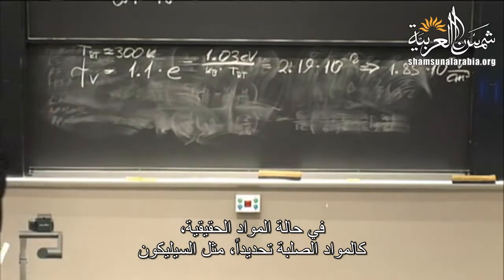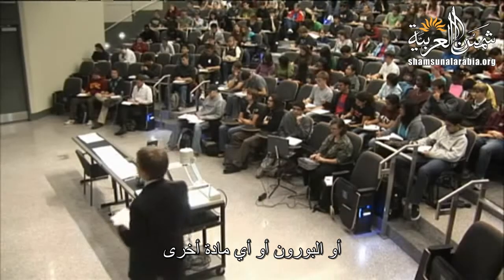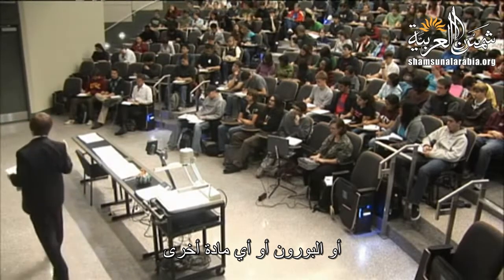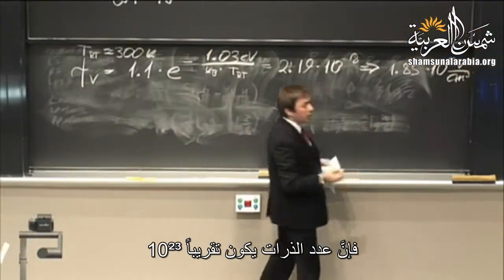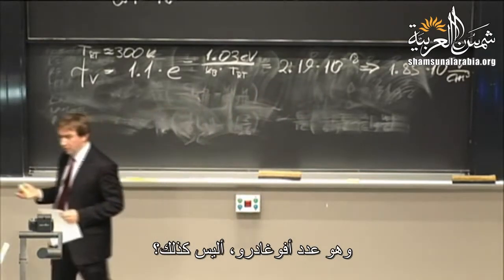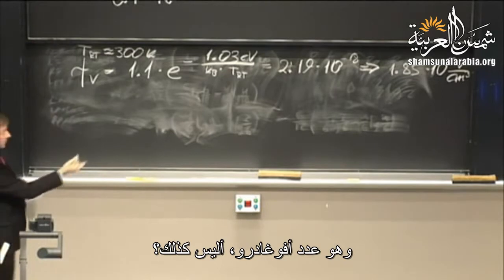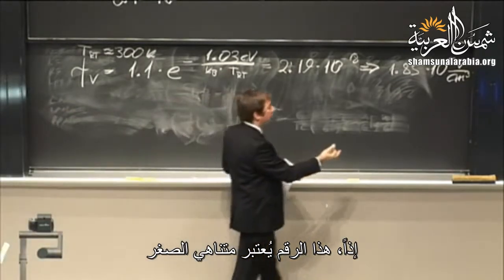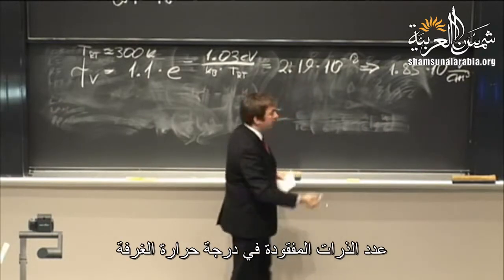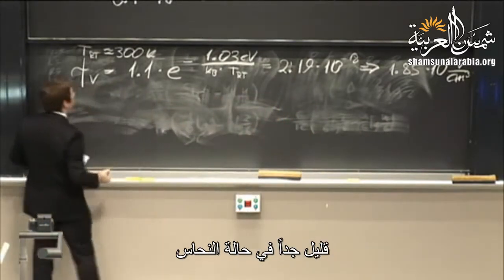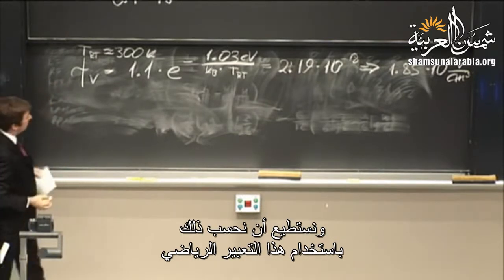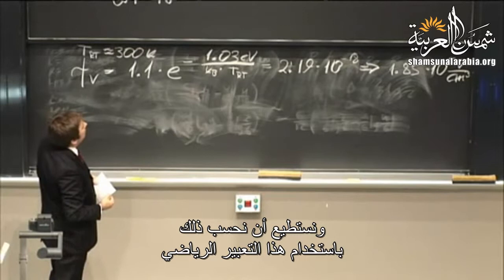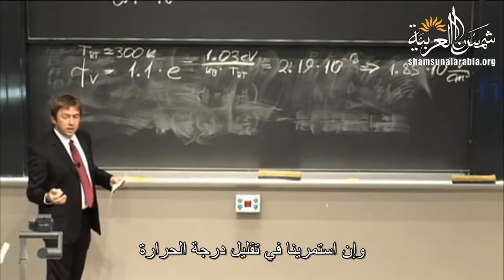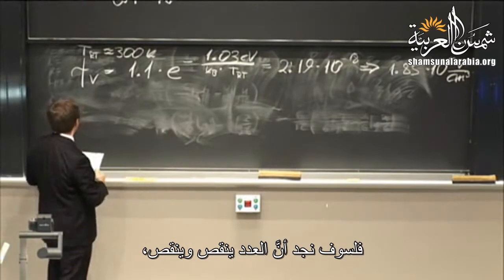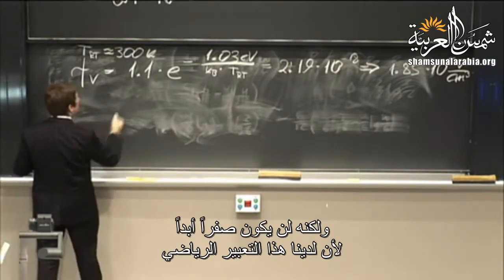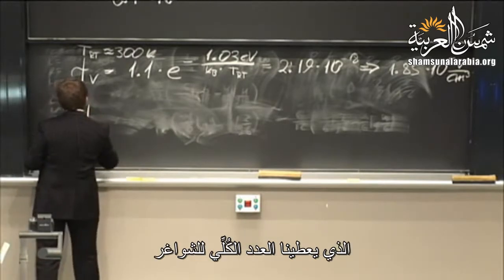And if in a real material, a solid material like silicon, for instance, or boron, or whatever you're interested in, your number of atoms is something like 10 to the 23rd, Avogadro's number, then this is actually a very tiny number. Compare 10 to the 5th to 10 to the 23rd. The number of atoms that are missing at room temperature is very low in copper, and we can compute that using this expression. However, even though it's low, it's not zero. And if we continue going down in temperature, we'll find that the number is lower and lower, but it never really goes to zero because we have this expression which gives us the total number.